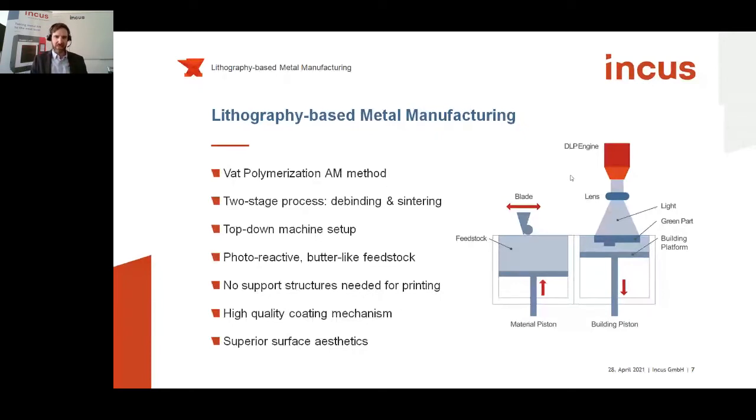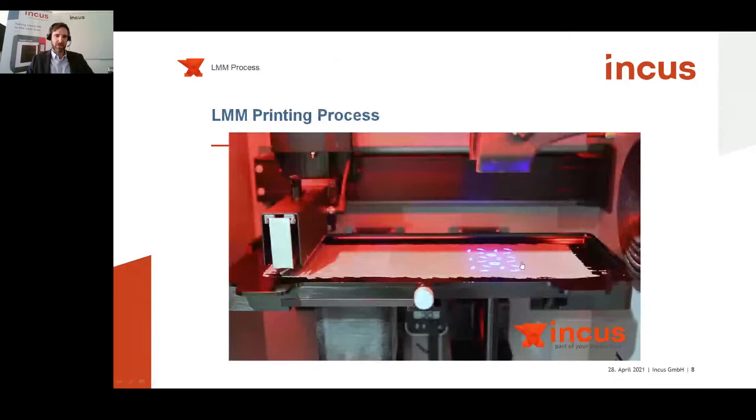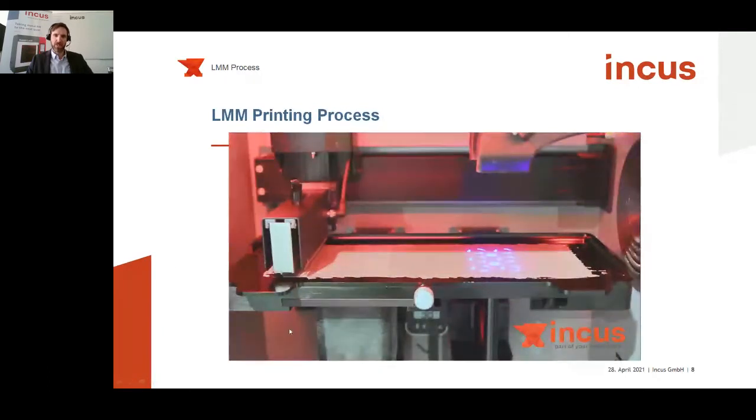The special thing, or the secret sauce for us, is the photoreactive butter-like feedstock. At room temperature, our feedstock, the raw material, is solid, and at coating temperature around 30-40 degrees Celsius, it turns liquid. So we always coat a liquid layer of material on a solid surface, and that allows us, together with the high quality DLP or projector unit, to create parts in the highest possible surface aesthetics and accuracy for metal additive manufacturing. What's also indicated in this scheme on the right side is that we don't need supporting structures to connect the parts to the building platform, and we can print overhang structures also without any connection to the building platform. I have a short video, I hope it runs smoothly for everybody, showing the printing process.